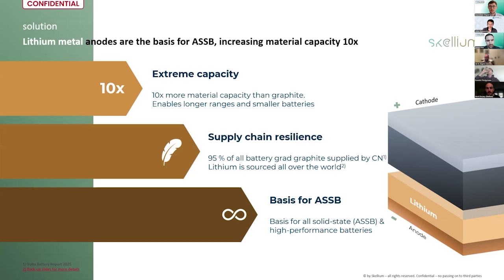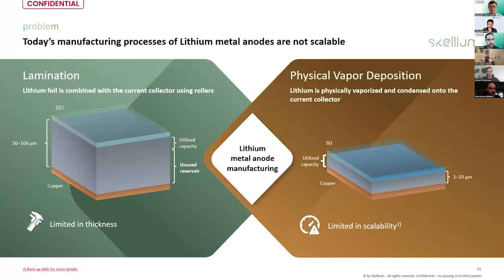Depends on how you want to frame it. What we actually do is manufacture the lithium, but we cannot use it only for solid states. We can also use it in a different way due to our process. The current process to produce lithium metal electrodes is, on the one hand, an extrusion and lamination process, and on the other hand, a physical vapor deposition process. So we have, on the one hand, very good commercially ready electrodes, but with a thickness of 50 to 100 microns, which is way more than you actually need.